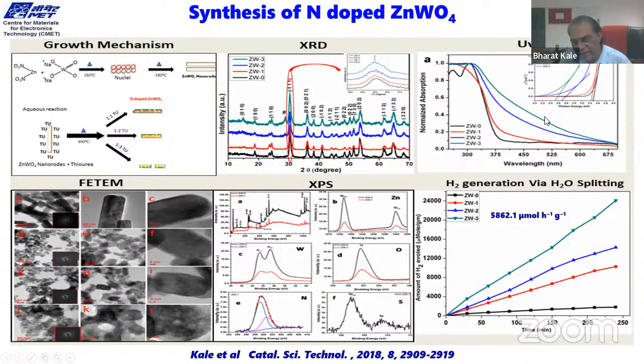And then the same ZnWO4 can absorb visible light in a bigger way. So this is ZnWO4 nanorods, and with nitrogen doping, we found that a porous structure is formed. These are nanorods of 50 nanometer diameter. You see these small holes here, white spots. They are small perforations in the nanorods, and that also helps for the production of hydrogen. And here you see how this nitrogen doping has increased it a lot. Nitrogen doping gave the enhancement in the hydrogen evolution.